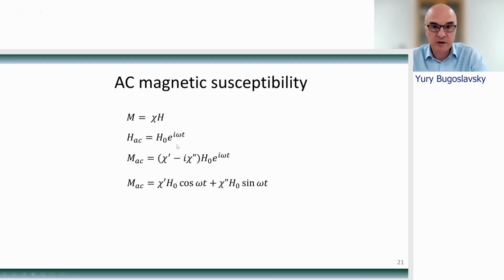If the field is harmonic, it oscillates at a frequency omega. The magnetic response will also come at the same frequency, but generally the magnetization will lag behind the magnetic field, and this is a genuine effect, not the measurement effect, but it's a genuine physical property. Often the magnetic structure simply can't respond instantaneously to changing field, and so the response comes with some delay. Mathematically, this means that there is a phase shift between the magnetic field and magnetization.